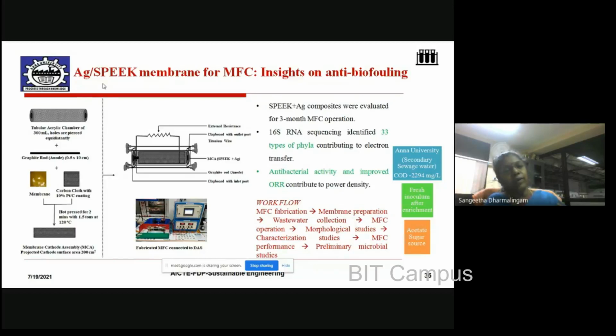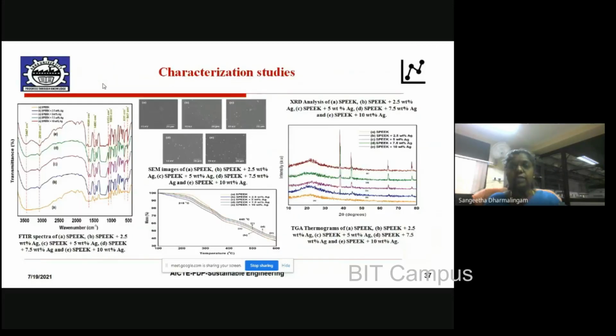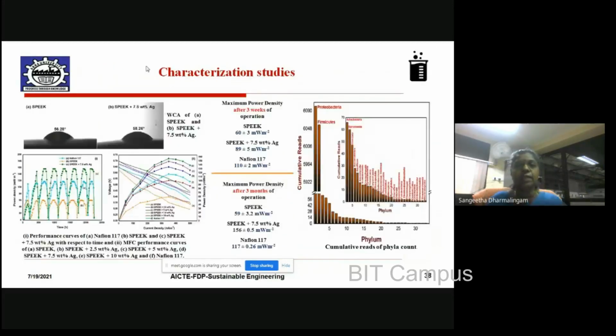Therefore, what we try to do is we started adding some anti-fouling agent. Silver is one of the best anti-fouling agents in order to prevent the adherence of the microbes on the membrane, and we tried evaluating such membranes. Okay, then we arrived at a situation where after 3 weeks it was 60 plus or minus 3 milliwatts per meter square, but after 3 months we were able to see that the performance increased because of the silver content.